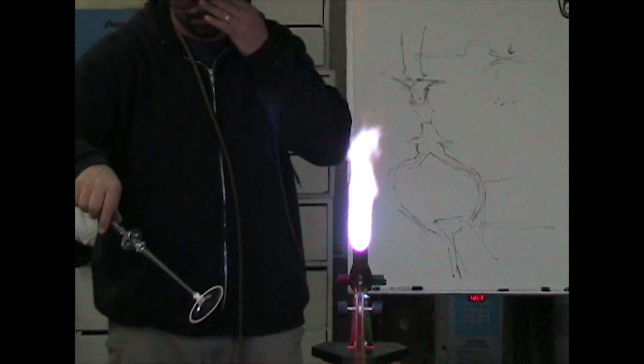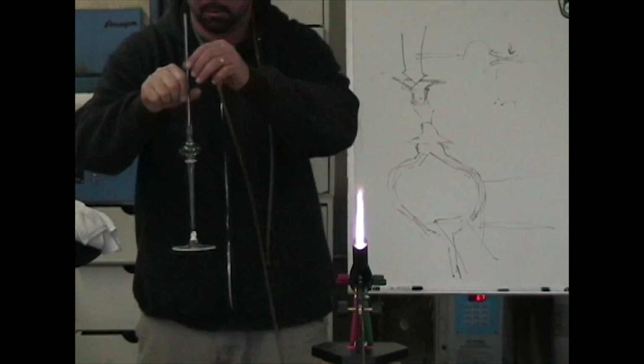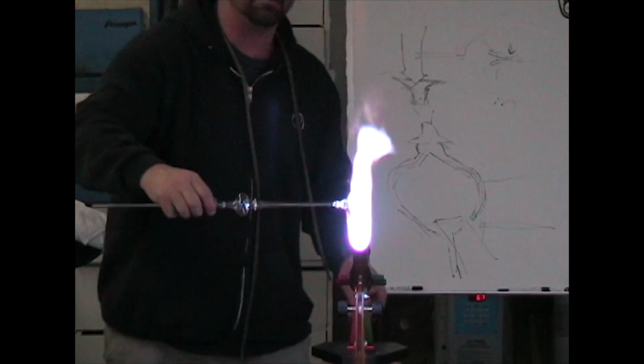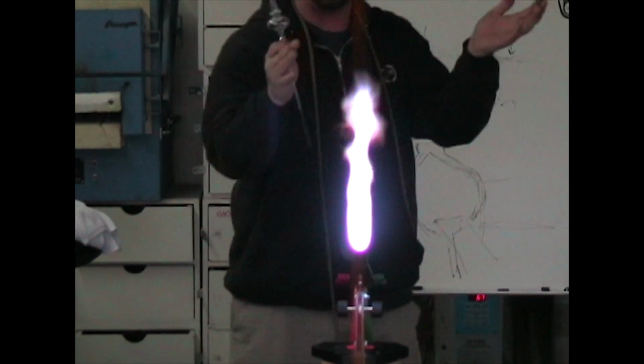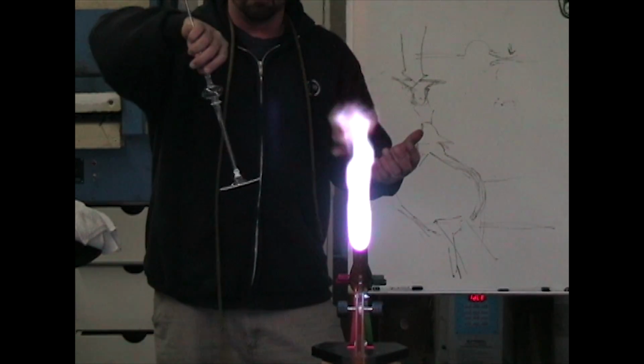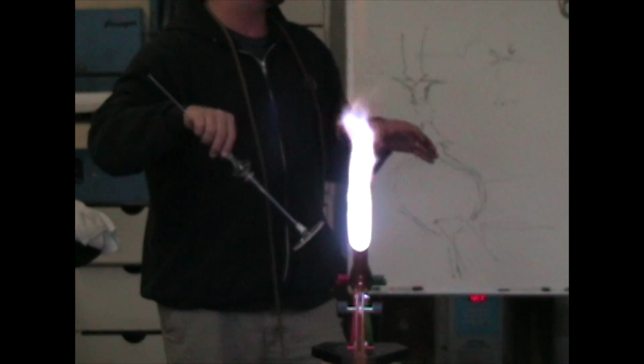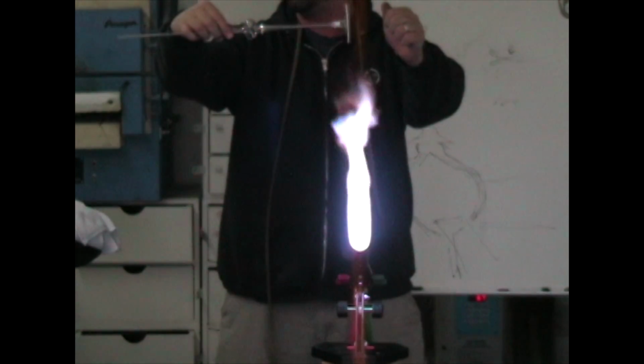All right, everyone got it? No problem. Now if you spin it out right, it cannot get any flatter. If you spin it out and move up so the edge of the foot can roll back, then sometimes you will get a foot that doesn't really sit flat all the way around and will wobble. Then you've got to go back and paddle them. But if you spin it out flat and don't kick the edges out, it should be flatter at that point than what you're ever really going to be able to get back to and paddle flat. Because inevitably, when paddling flat, you'll hit one side before the other.